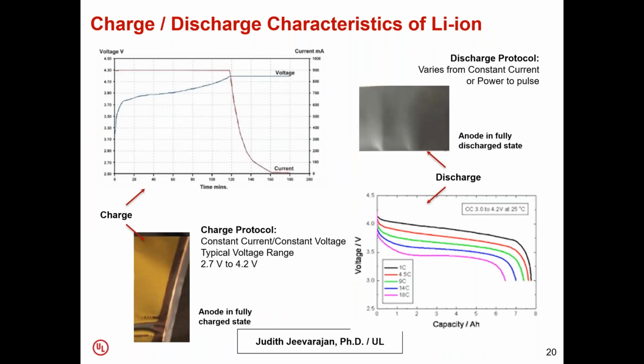So this chart shows the general charge and discharge characteristics of a lithium-ion cell. Typically, a lithium-ion cell is charged using a constant current and constant voltage protocol. At the end of the charge process, when you look at the anode, you'll see that it has a gold color. This shows that lithium ions have intercalated into the carbon matrix, and that provides a gold color. When the discharge happens, when all the lithium ions go back to the parent cathode, the anode has no lithium ions and so has a grayish black color.